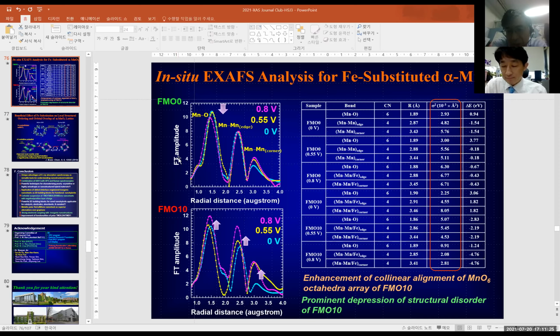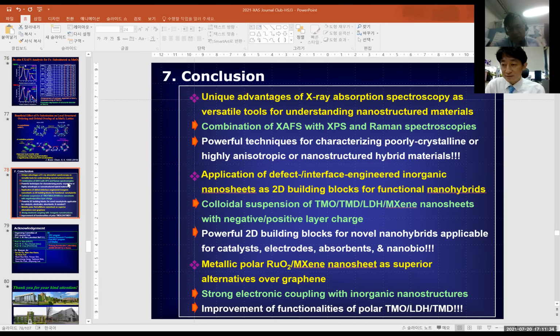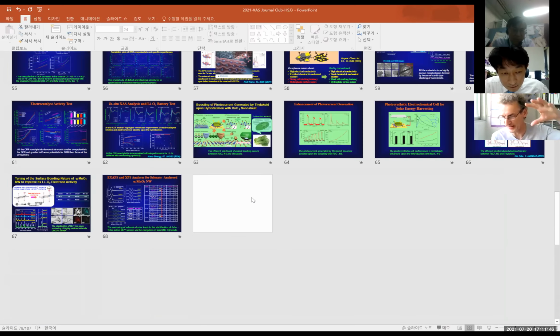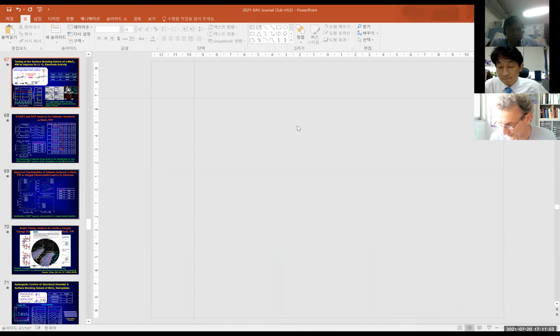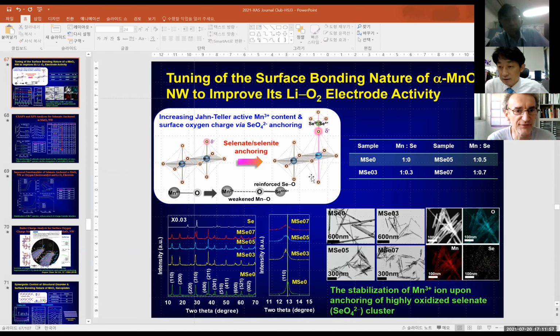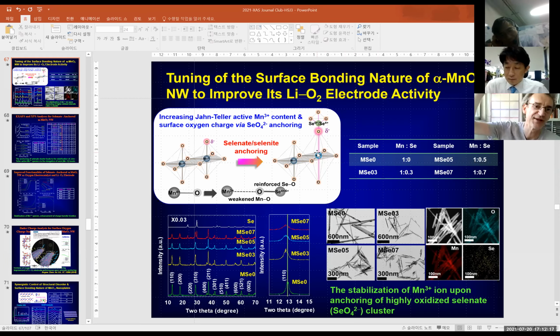Any other questions? Please switch on. Yes, may I ask a question? It's related to what was just said about the manganese 3+ Jahn-Teller story. I didn't fully understand. You anchor this selenium oxide, if I understand well. This distorts your structure, and thereby you said you stabilize the Jahn-Teller distortion. But from my understanding, Jahn-Teller active means there is a symmetric structure first, and then because you have manganese 3+, you get a spontaneous deformation of your octahedron. So this is not the same. If you form a chemical bond, then you distort the system chemically, and it is simultaneous. This is no longer Jahn-Teller, is it?